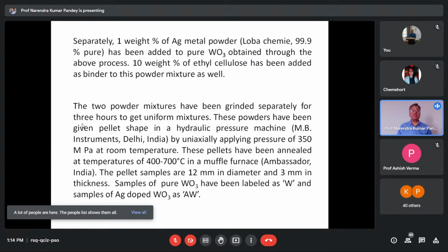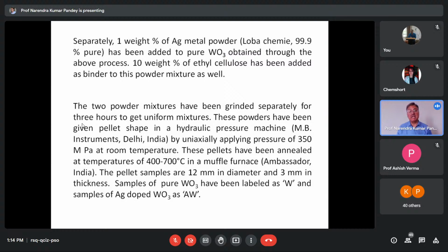Now, these powders were given pellet shape in a hydraulic press. Then they were annealed. The pellet sample that I am going to present results for had 12 millimeter diameter and 3 millimeter thickness. Let us say if it is pure WO3, we will call it W, and if it was Ag doped WO3, we will call it AW.